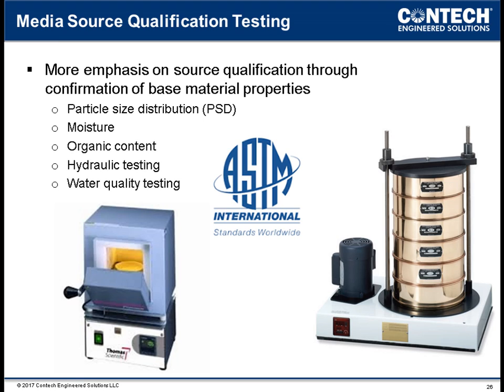There needs to be more emphasis on source qualification. Verification testing alleviates many of the issues observed with public domain bioretention systems. Tests should follow approved testing methodologies where possible, just to provide equal evaluation among different media. Excessive nutrient leaching, like I said, due to high P-index materials, or metals leaching due to unqualified compost can occur without proper testing to evaluate the composition of materials in a bioretention blend.